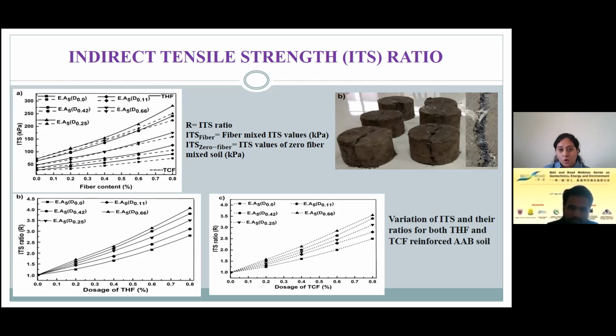We are in the process of implementing this entire process in the field. I have not presented the results here, but we are already in the process. So what we are basically doing is we are preparing this at large scale, and then we are storing this particular binder for around 24 hours. We are seeing that within 24 hours maximum of the heat is dissipating, and then we are using a rotavator and mixing it with the soil. So this heat evolution is a real challenge.